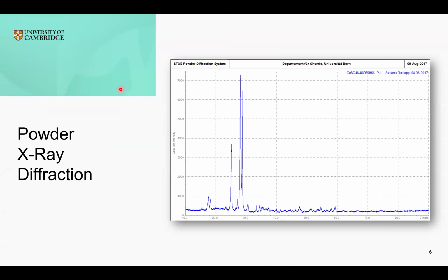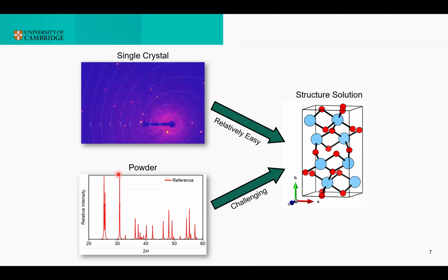So let's see how we can use then experimental powder diffraction to guide the structure predictions. First, we know that to obtain structural information from a sample, X-ray diffraction is usually the best way to go, even if it's not the only one. If the sample that we have is a nice single crystal, then the structure solution can be relatively easy. This is not the same if the sample is a powder, since we are basically merging all the peaks of our diffraction along just one dimension. And this causes some loss of information and makes the structure solution quite challenging.